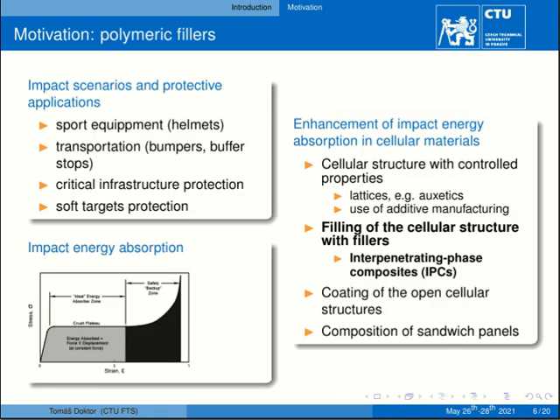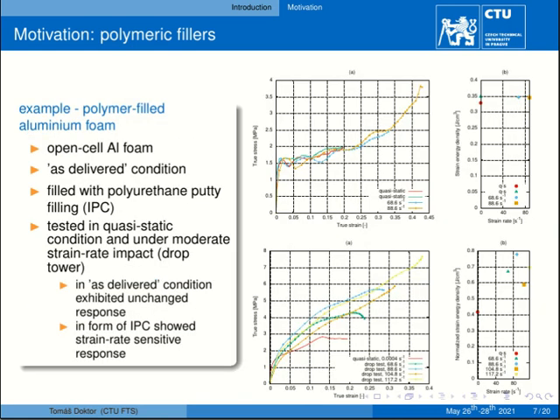Directions to enhance the impact energy absorption consists in filling of the cellular structure with polymeric fillers. Together with the lattice, the filler form interpenetrating phase composite. Here you can see some results of our previous research, which was focused on interpenetrating phase composite made from open cell metal foam and polyurethane putty. And the lower and upper diagram show the difference between the behavior of the plain metal foam and the IPC, which exhibited strain rate sensitivity even at low impact energy induced by a drop tower.